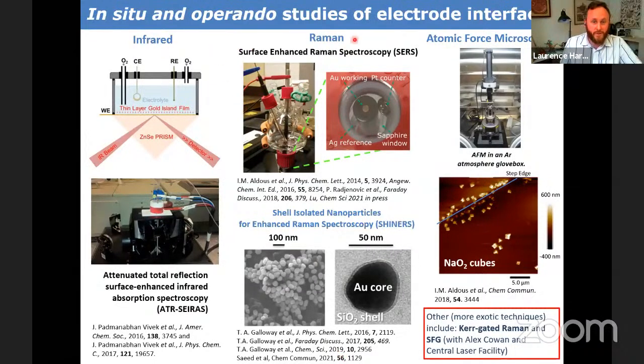We do this with the more traditional surface enhanced Raman spectroscopy, where we electrochemically roughen a gold working electrode to give us a nanoscale roughness. This gives us the surface plasmon to enhance the Raman signal. We have this beaker cell here, a three electrode cell with a reference electrode and counter electrode, and here's our nano-roughened gold. We can then mount this on our Raman spectrometer, do the electrochemistry, and then shine the laser, as I'm doing with my laser pointer here, and under potential control, collect the spectrum and see observed changes at the interface.